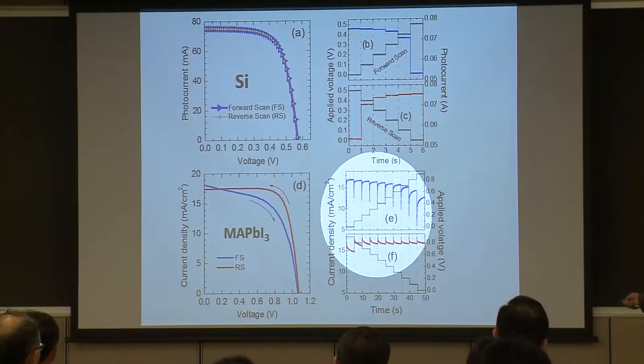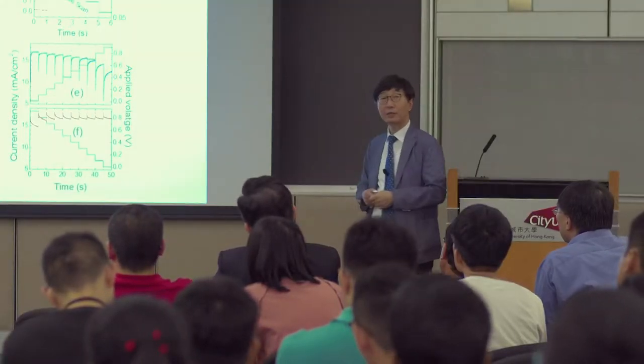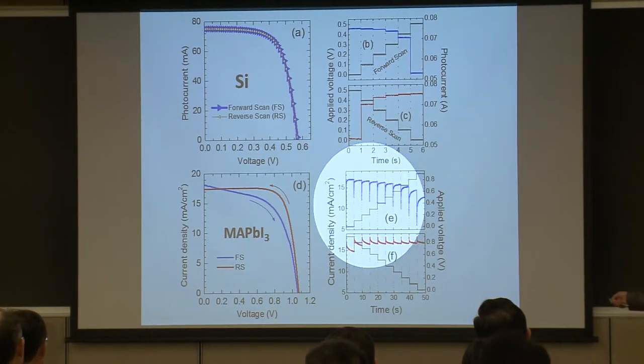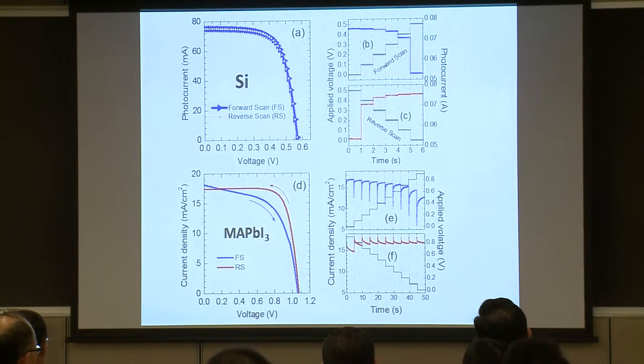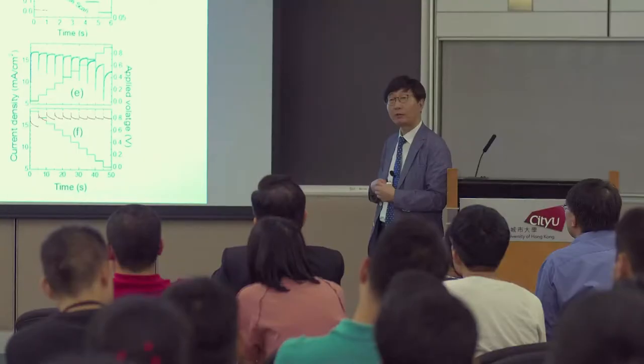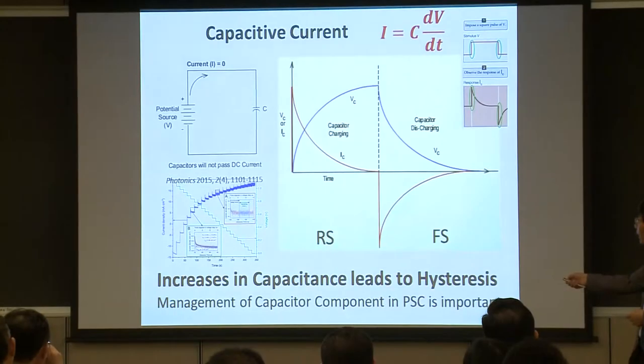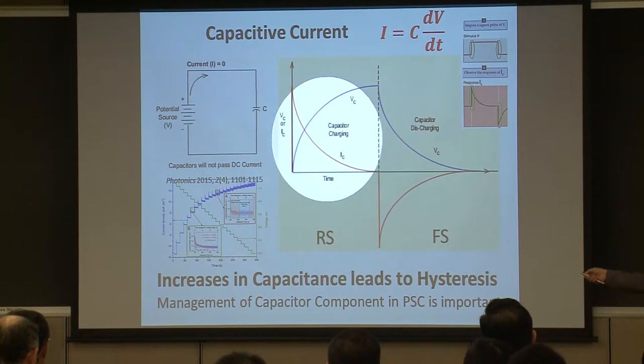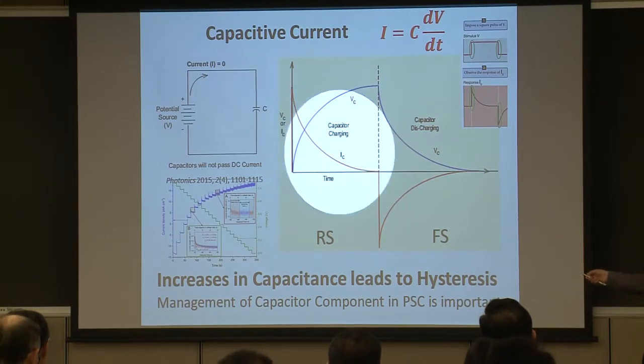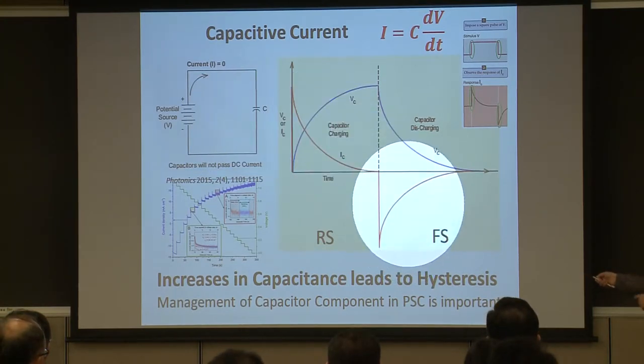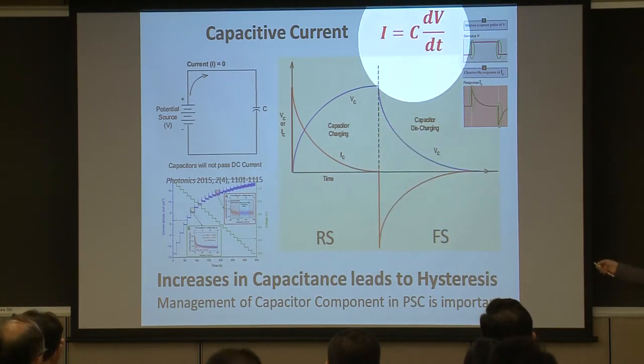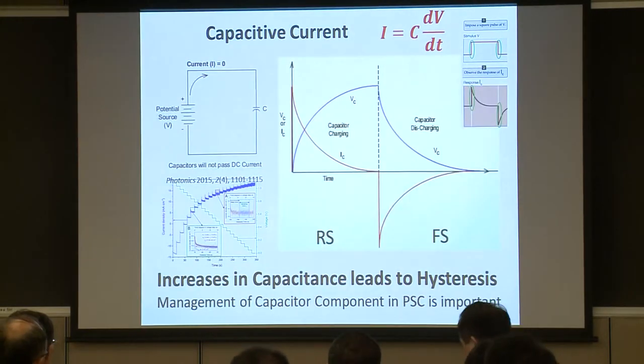If you take a look at a voltage stepwise scan, there is a high range of current that then decreases with time, or the opposite, a very low current that then saturates with time. This profile is well known as the capacitive current. For instance, if you construct a capacitor and then apply a bias, you have a charging condition. The capacitive current decreases with time. For the case of the discharging curve, the shape is the same, but the polarity is different. This is because the capacitive current depends on the change of voltage with time.